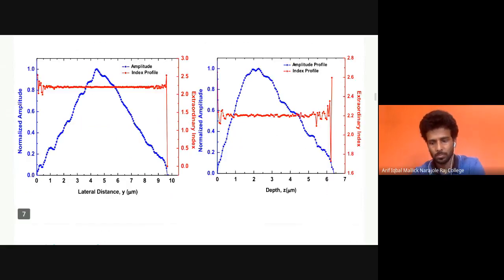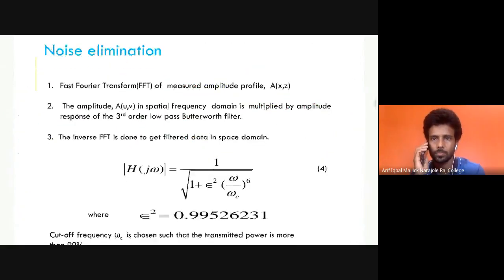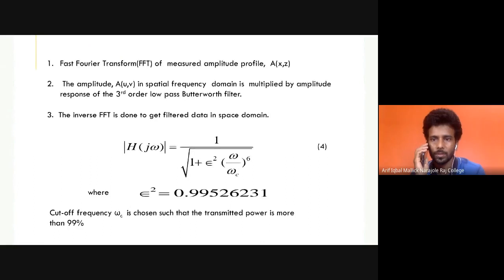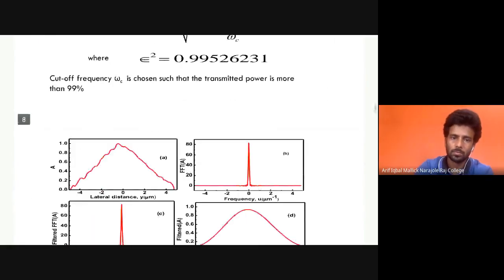The noise elimination procedure: first, Fourier transform of the measured amplitude profile in the space domain, and secondly, the amplitude in the frequency domain is multiplied by the frequency response of the third order low pass Butterworth filter. Finally, to get back the amplitude profile in the space domain, inverse FFT is done. This is the transfer equation, transfer function.